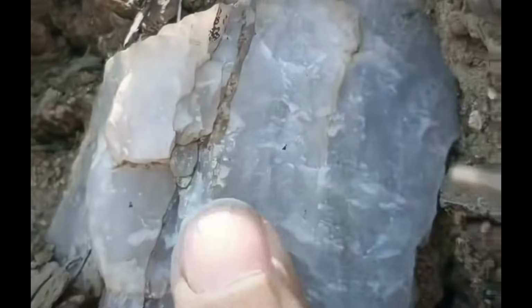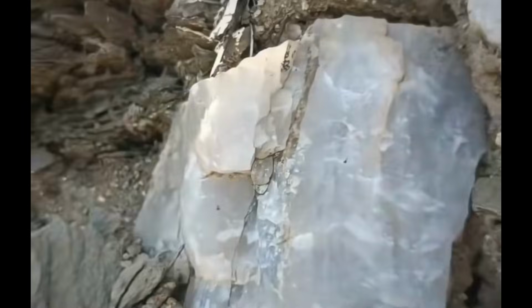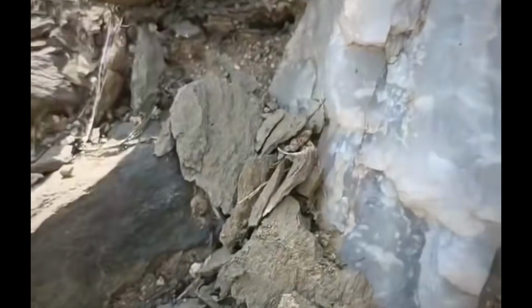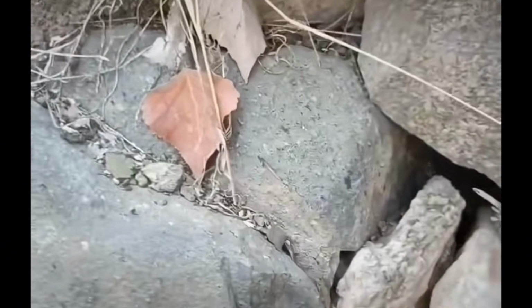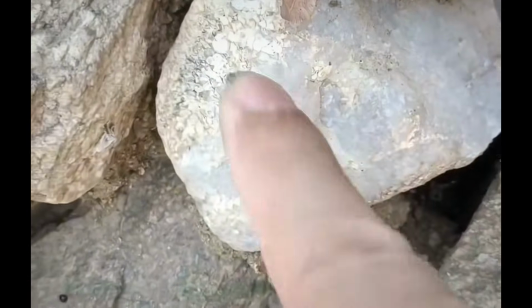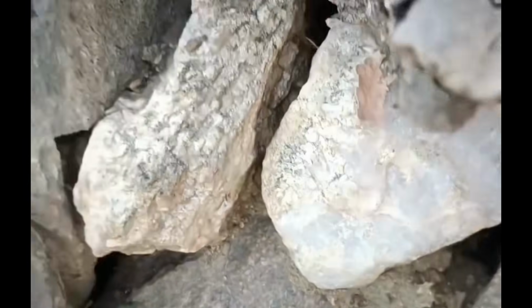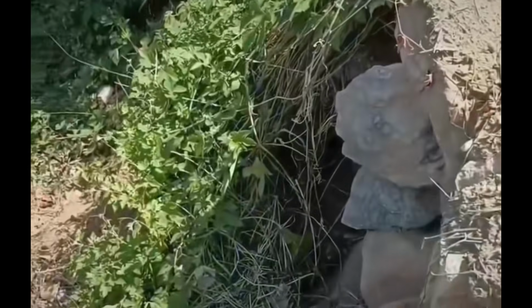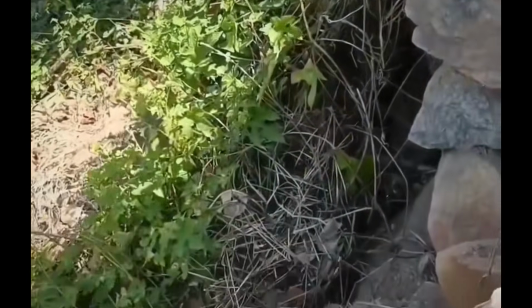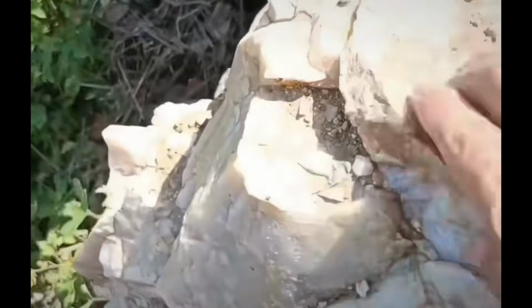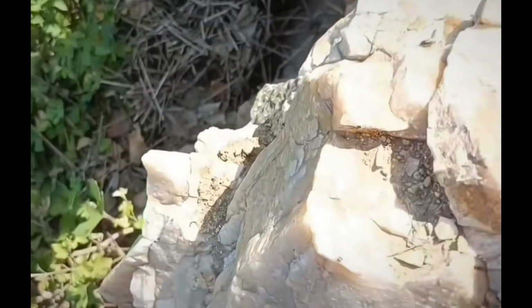But more telling were the changes in float material as distance increased. Closer to the outcrop, fragments had sharp edges, clear quartz, and visible sulfides. Farther out, the quartz was more rounded, less distinct, and lacked visible mineralization. That drop-off helps estimate how far gold-bearing material travels before dilution, important for tracing placer sources or identifying secondary enrichment zones. It also narrowed the target zone for further sampling, between 5 and 20 meters upslope, where the vein's projected